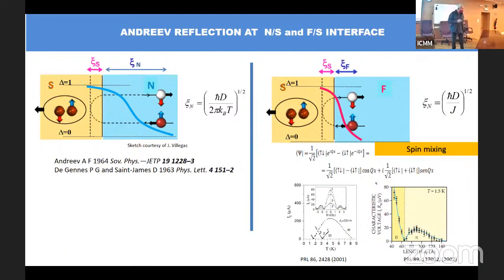So the way people have measured in practice the zero pi transition is by a drop to zero of the critical current. This is the result of the Jan Aarts paper, and this is the Courtois and Marco Aprili paper. Basically, they claim a zero pi transition by the critical current going to zero. I think we may feel this, but this is not going to be a zero resistance state, but a background resistance state.